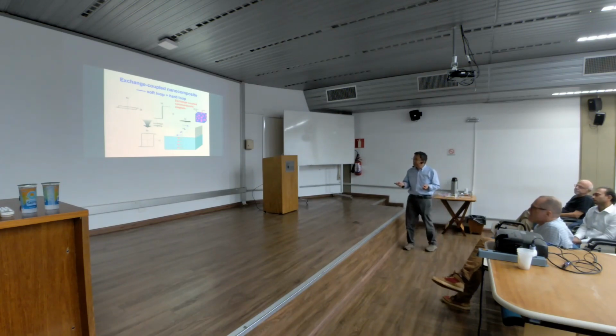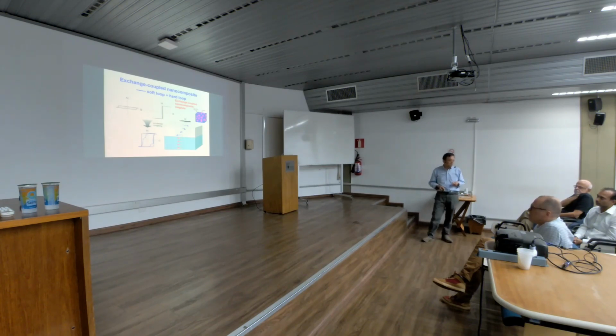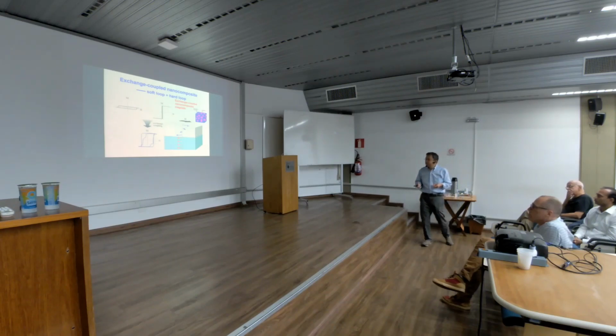If you just mix them in a random way, the exchange coupling won't take place. What you obtain is the blue loop. See, it's a big kink. I don't know how many of you, when you measure your loops, get these kinks. Very common, actually. In this case, the mixture of hard phase and soft phase is a superposition of the two loops. Mathematical superposition. There's no exchange coupling. So in this case, you won't have any enhanced energy product. You either get the energy product of this or this. So that's not what we want to do.